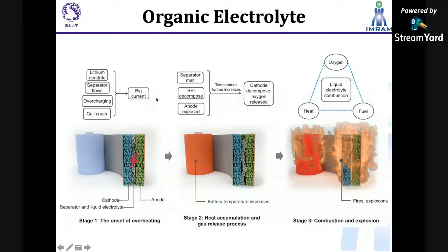So how does the explosion take place? This shows stage 1, the onset of overheating. When your battery is charged and discharged n number of times, several side reactions take place on the graphite, on the anode, or else on the cathode. These side reactions cannot be avoided. Because of them, lithium dendrite forms, that is, lithium metal is deposited over the surface of the anode. During longer usage, the lithium dendrite grows longer and longer, pierces the separator, and contacts the cathode material. Therefore, there is a short circuit between the cathode and the anode, and this short circuit leads to a large current.